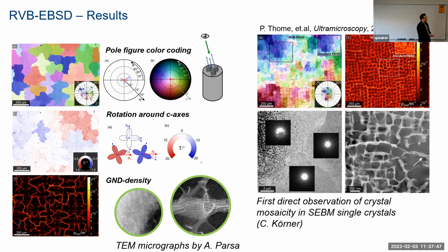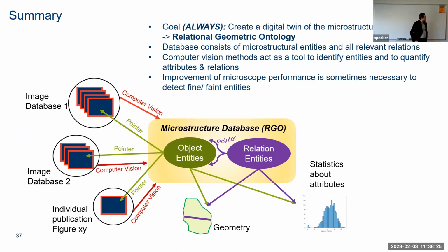And what was very, very nice, we were actually the first that investigated 3D printed single crystals. So our colleagues in Erlangen, Professor Körner, she's able to build up single crystalline material by additive manufacturing with the SEBM procedure. And we were the first that observed, well, also these materials exhibit something that is similar to a crystal mosaicity. Probably the mechanisms why are completely other ones. There are certain ideas. We are not 100% sure of how this is, but yeah, maybe we can talk about this later.